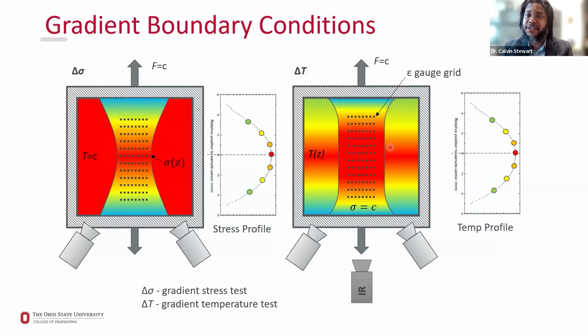But furthermore, say we make a specimen with a uniform gauge section, so one value, constant stress, but we design the temperature environment so that it is a temperature gradient that is quasi-static. So there's a gradient, but it's stable. Then we can get a temperature profile that changes along the sample, and then we can take little mini strain gauges across the correlations that we have and get 100 test results, again, from a single sample. So this parallelization, this massive ability to parallelize, takes us from having to do so many of these standard tests to say, you know what, this isn't a good chemistry, this isn't a good heat treatment, to be able to do 1, 2, or we'll say 5. Why don't we say 5 of these tests in order to screen the resistance of a candidate composition, right?